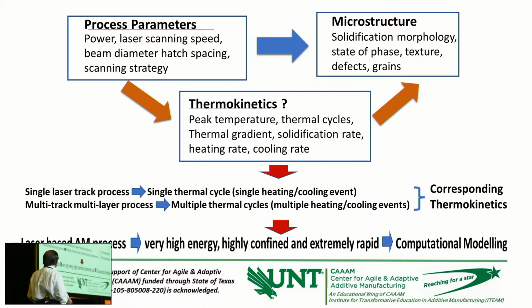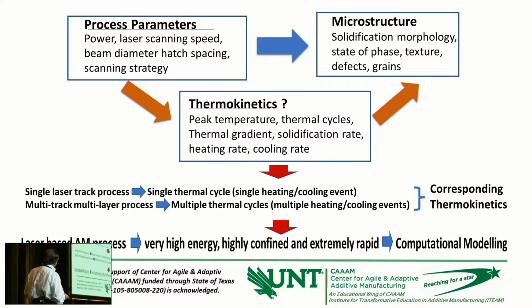That means you have to look into the peak temperature developed in the process and the thermal cycles, because thermal cycles are produced during the single layer, and when you make multiple layers, more thermal cycles are created. So very complex thermal cycles are involved. Then associated with that are thermal gradient, solidification rate, heating rate, and cooling rate. All these things depend on the process parameter combinations, and that will control the solidification morphology.